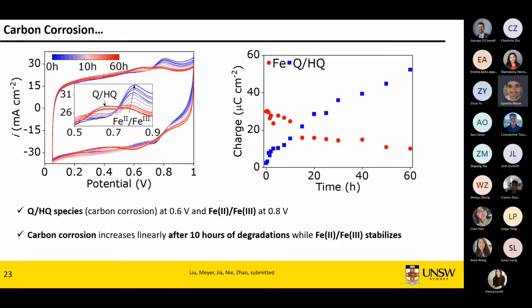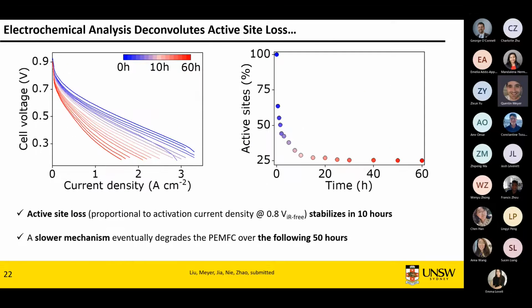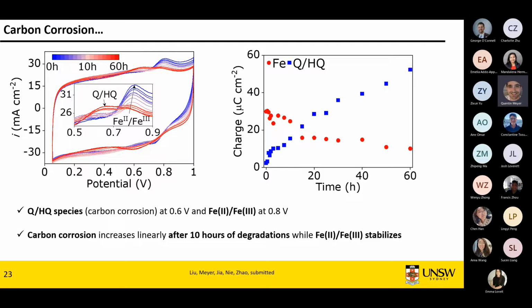And what we've done is try to do a bit of fitting of these two peaks to get the peak area, which gives you a sense of the charge allocated to both processes. What we've got from here is we're losing our iron very quickly. It looks similar to this one, just not quite as clean to capture. And then for our carbon, we get a first increase in the first maybe 10 hours. And then in the next 50 hours, you get a linear increase. So what's likely to happen is in the first 10 hours, you have hydrogen peroxide happening, which leads to a very fast carbon corrosion. And then it's just natural corrosion of amorphous carbon products in the electrode.